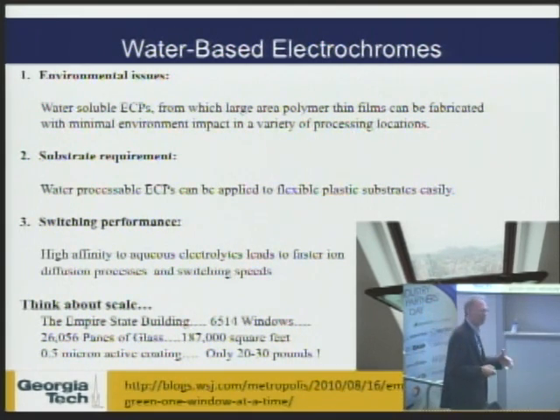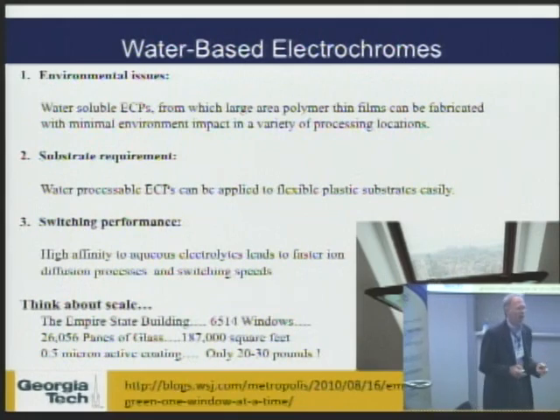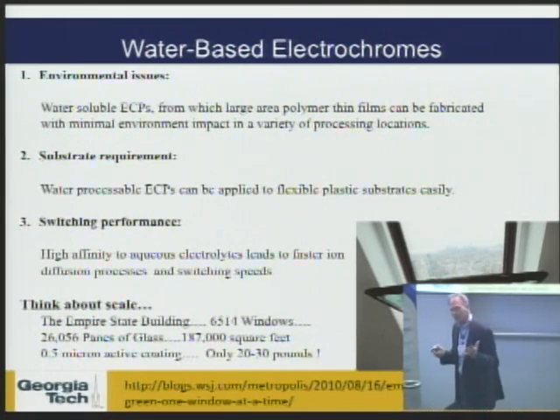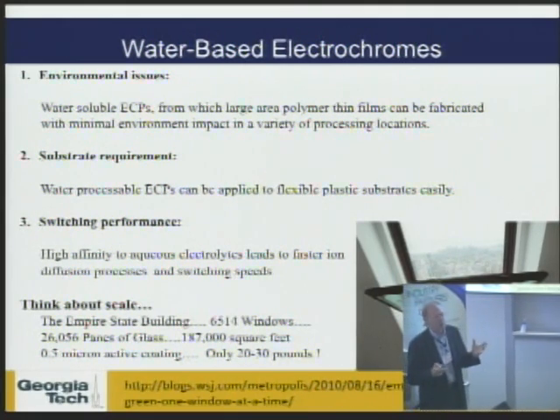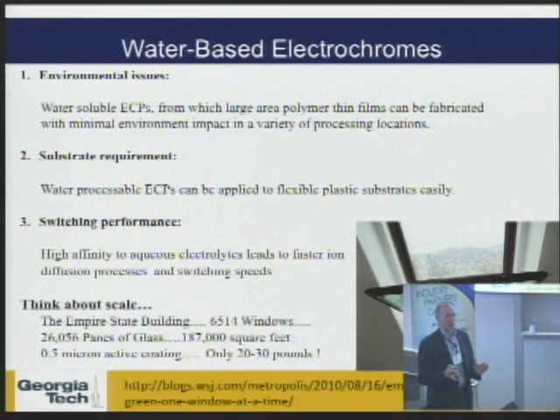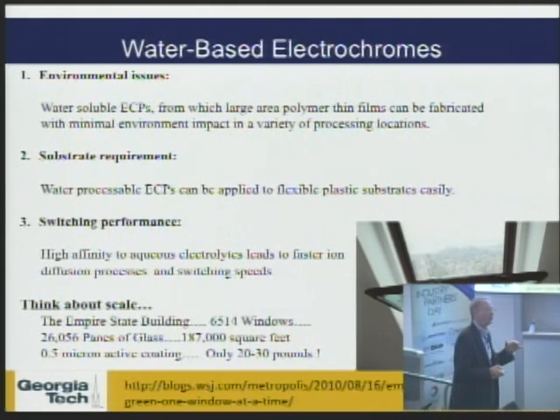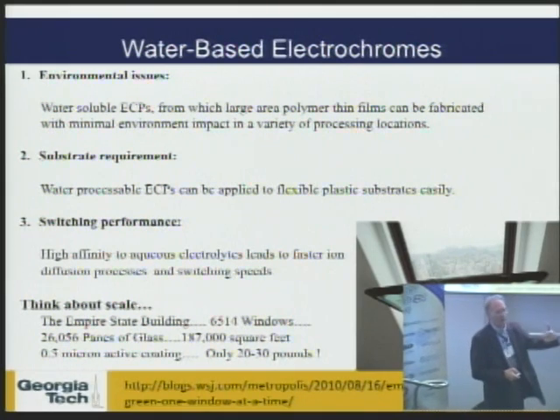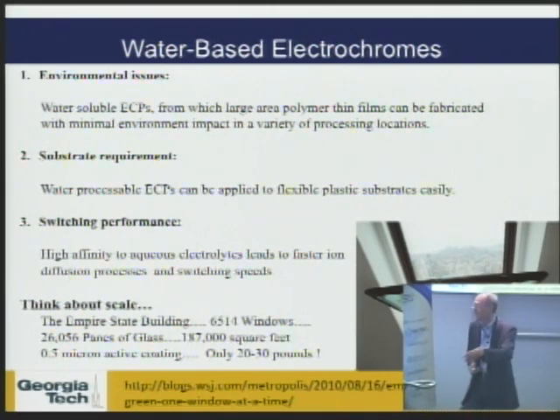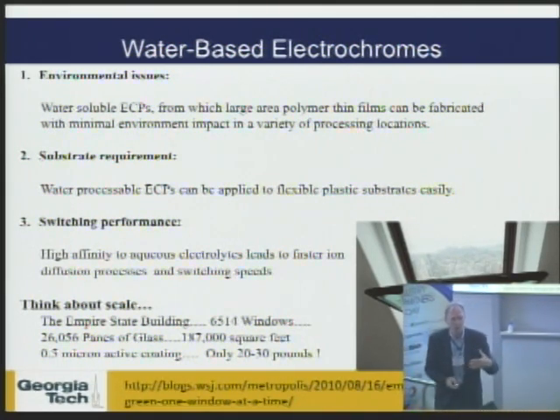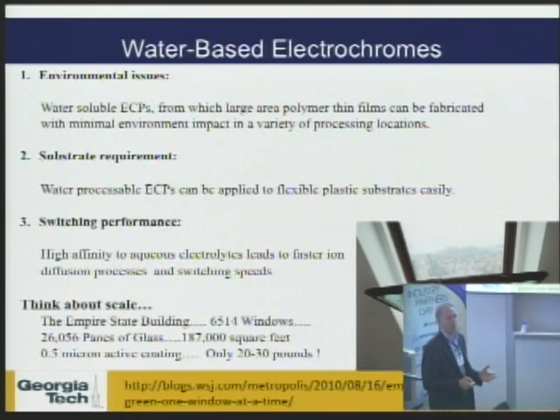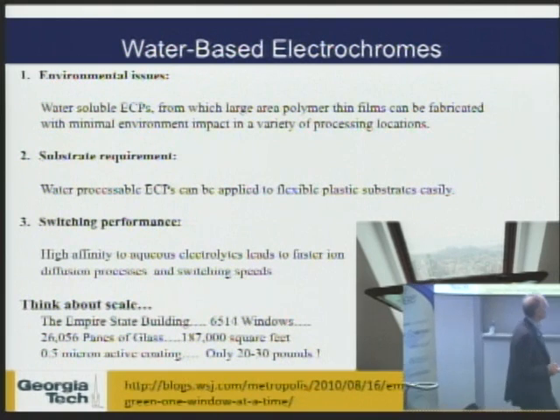And so using chemistries that might involve Suzuki chemistry, Stille chemistry, direct arylation chemistry with palladium, this is okay, because you're able to make a small amount and apply it to a large project. But where the gain is, is when those materials are then sent on to the engineering company that's going to be doing the processing, and they don't want to use dichlorobenzene, they don't want to use toluene, they can use alcohols, they can use water, etc.